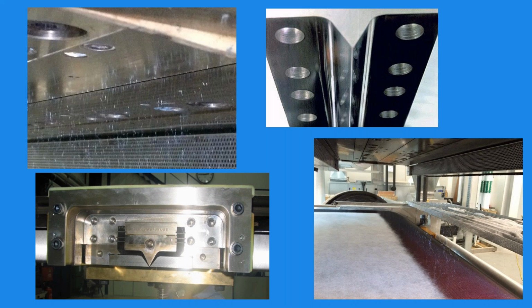So you want to make sure your BFE is high. When she's talking about manufacturing, I guess she means the melt blown manufacturer. That is a discussion, a good heart-to-heart, you need to have with them. They should be providing data for at least every parent roll. A parent roll is, you're making this stuff 1.6, 2.5 meters wide, it goes onto one big roll, and then it's split into smaller rolls. You should at least get data on each parent roll. So it's fiber size, pressure drop, what's called the air permeability, and bacterial efficiency if that's what you need.